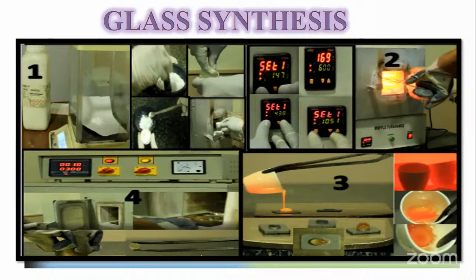What we try to do is initially set it at 150 degrees Celsius, so we are trying to expel the hydrates. For 150 degrees Celsius, we try to hold it for around 20 or 30 minutes. And later we try to switch it to around 415 to 420, or 430, 440, up to that